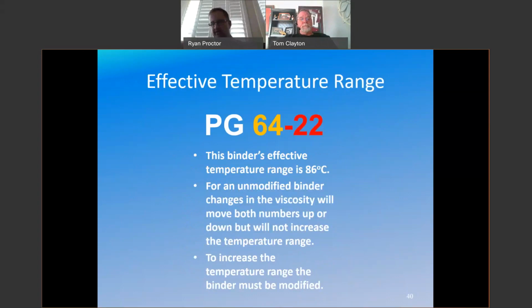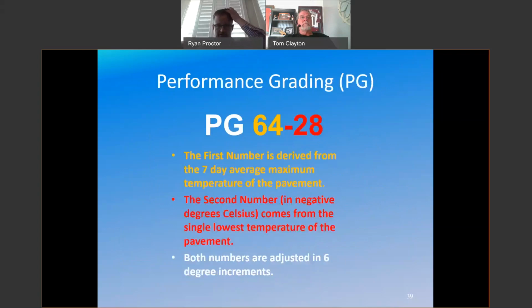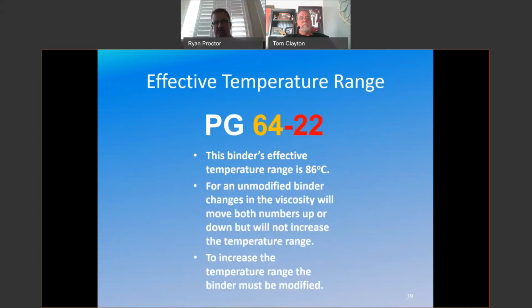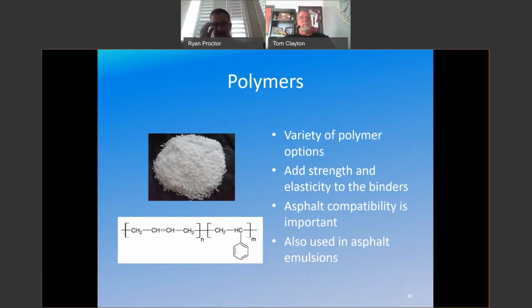Another thing to mention before I talk about some modifiers is effective temperature range. Again, there's more to a pavement's performance than the binder, but what we are saying is that the binder in this case should perform in the temperature ranges of 64 to negative 22 degrees Celsius. And the range for that binder is 86 degrees. So an easy rule of thumb, if you want to determine if a binder is modified or not, is if it's under about 92 degrees Celsius, it's usually unmodified. If it's over that, it's a modified grade. So 64-28, if you take the difference between them, we're at 92, it's a modified grade. 64-22 is not.